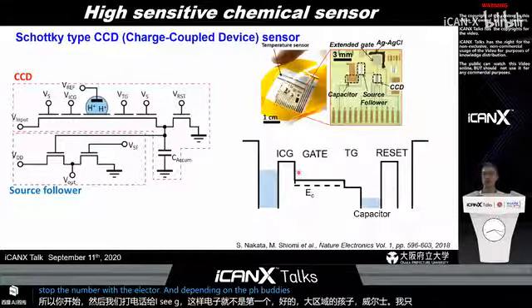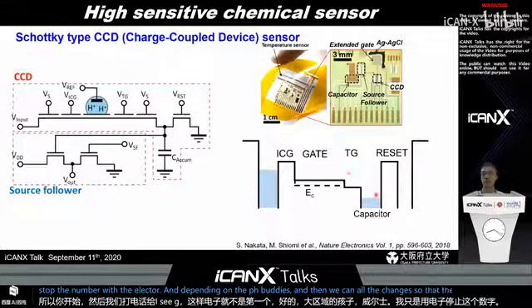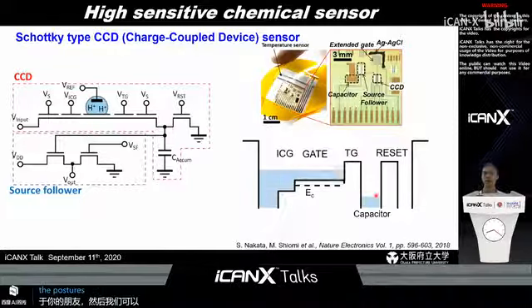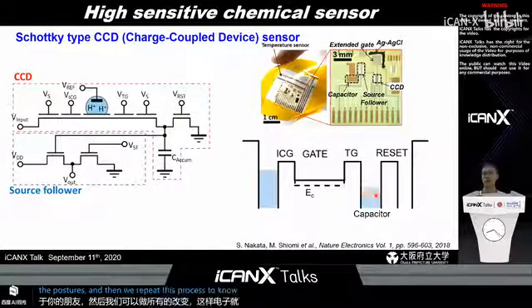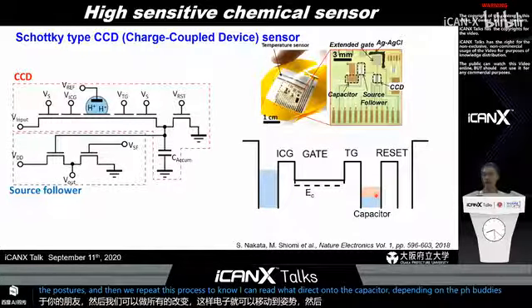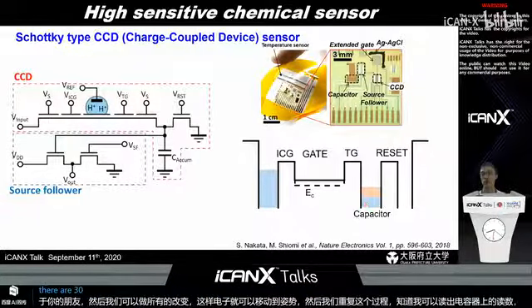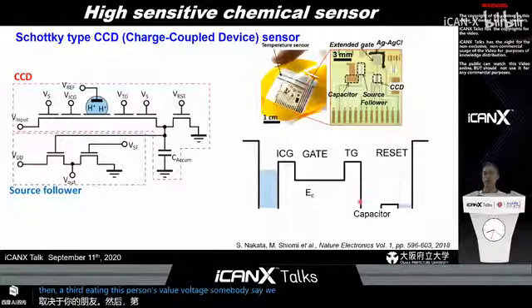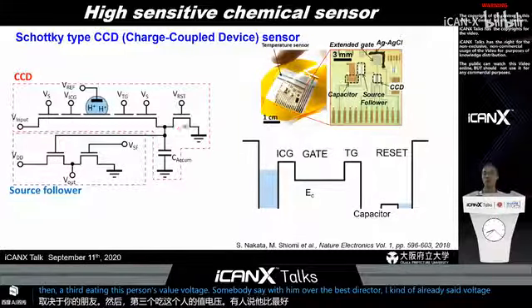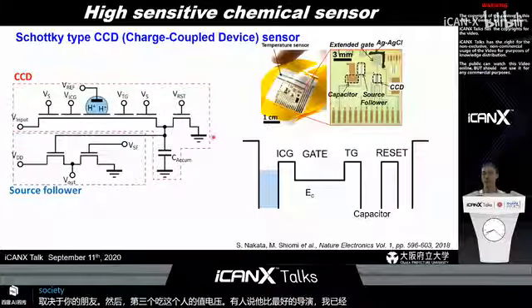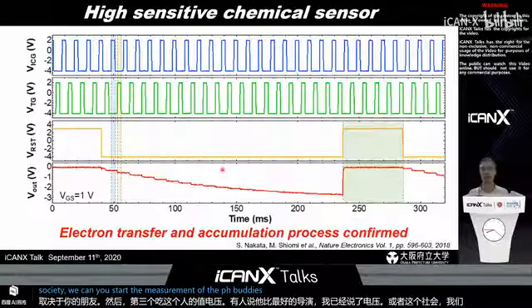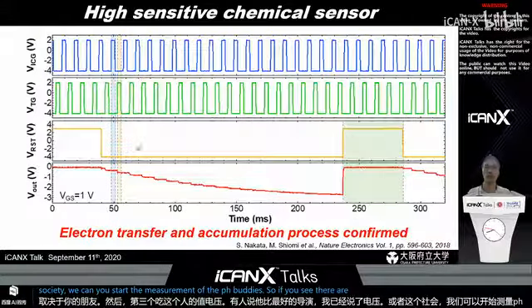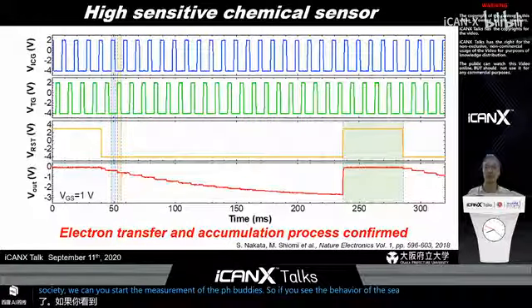And then we turn on the TG so that these electrons are moved to the capacitor. Then we repeat this process to accumulate more electrons in the capacitor depending on the pH values. After reading the capacitor voltage, we remove the electrons by turning on the reset voltage of this circuit, so that we can restart the measurement of the pH values.